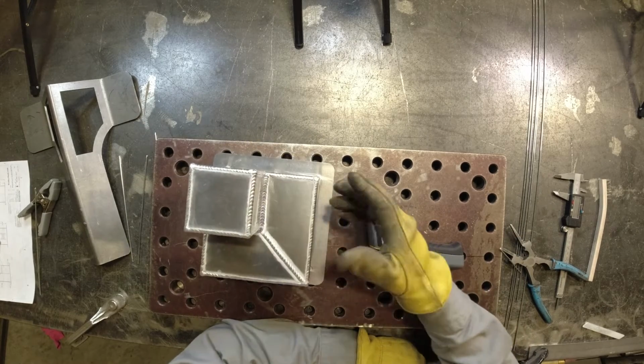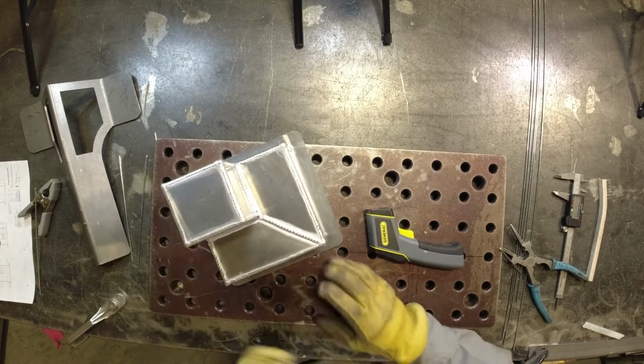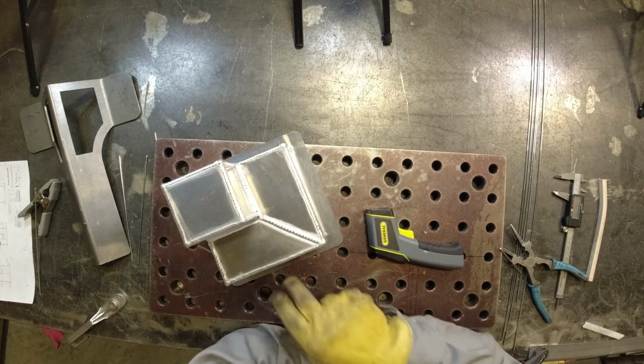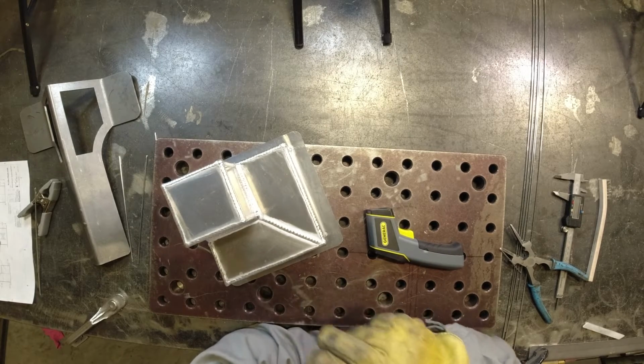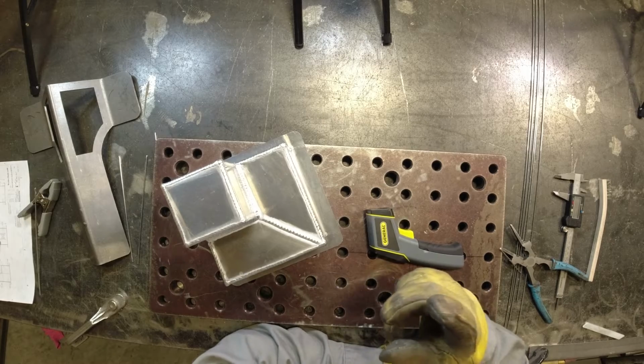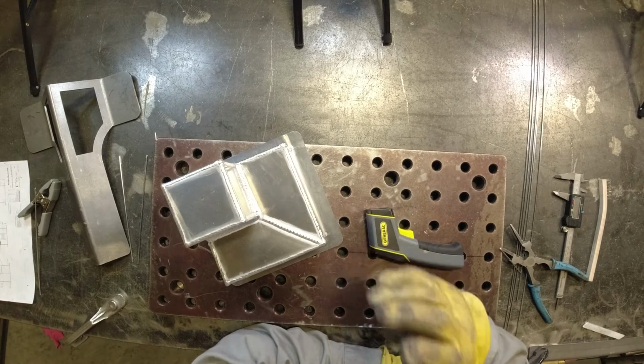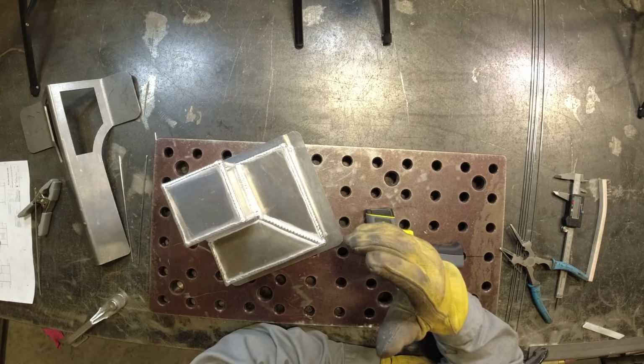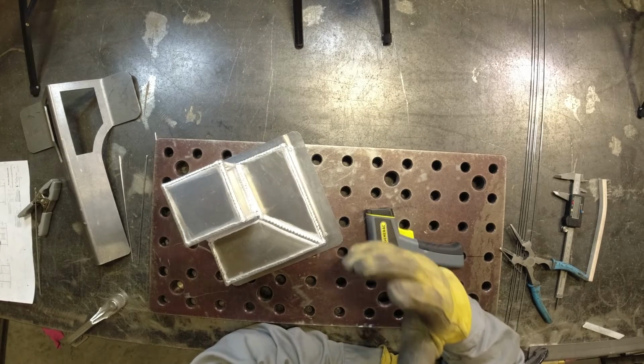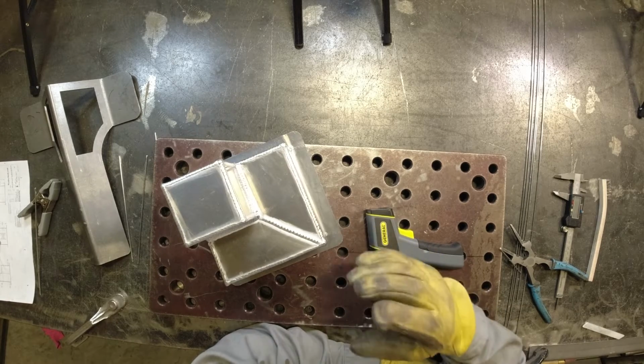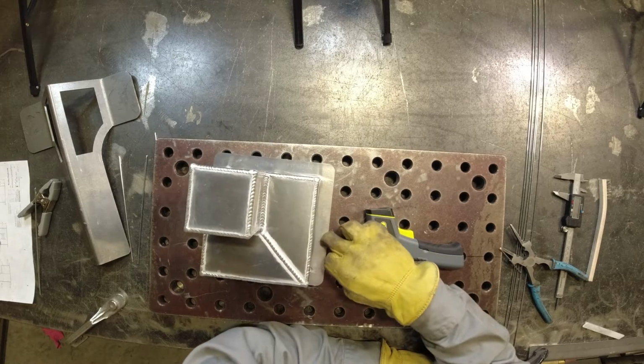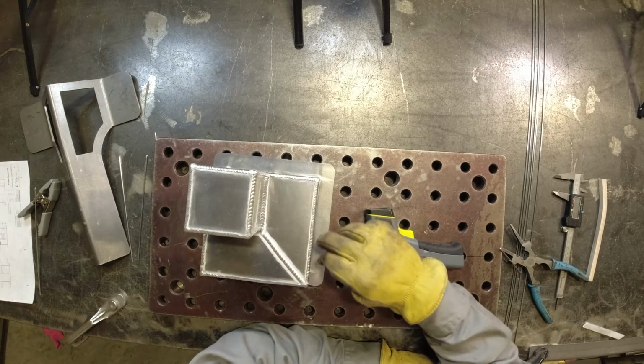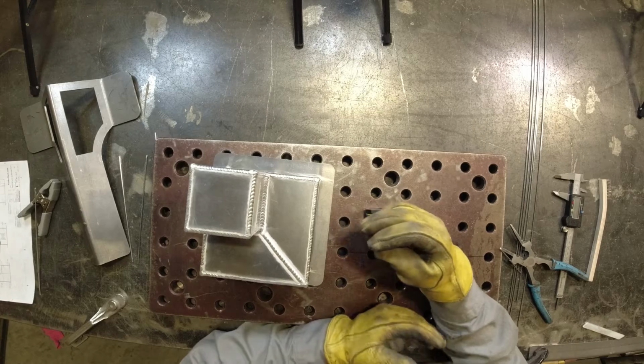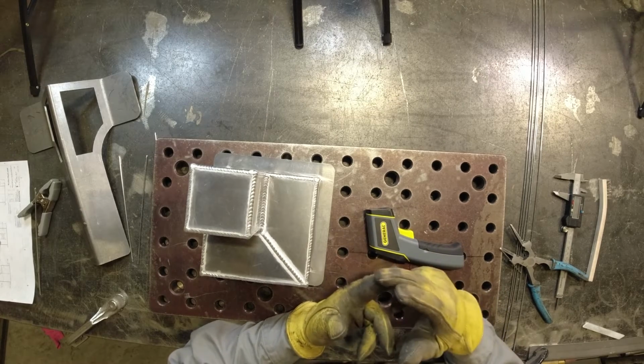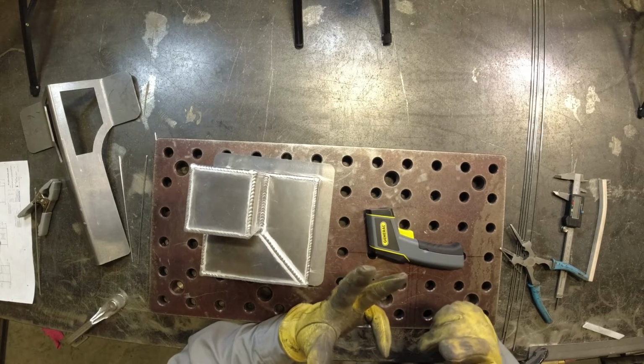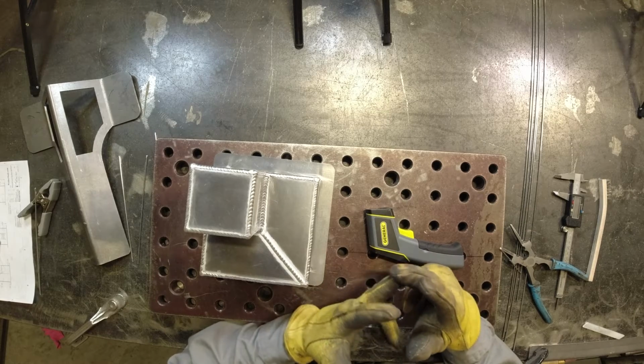And the reason why we weld the fillet weld on the bottom last is because it requires the most amount of heat for 2 reasons. One reason is that a fillet weld and its geometry naturally needs more heat than a corner joint to make a good weld. And that's why a lot of people struggle with fillet welds while welding aluminum TIG, is because they don't understand that it needs a little bit more amperage, or that you can have a little bit longer of a tungsten stick out.